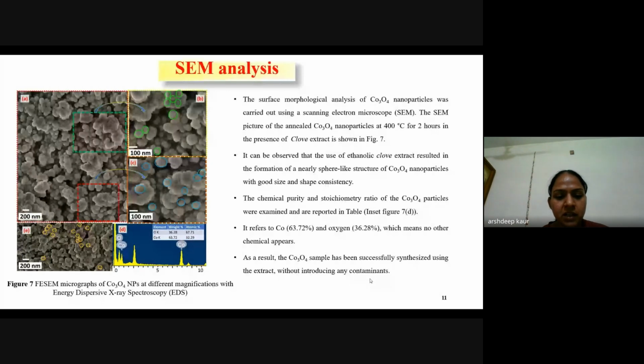In the EDS X-ray spectroscopy, it shows that cobalt has 63.72% and oxygen has 36.28% weightage of the particles, which means no other chemical appears. As a result, the Co3O4 sample has been successfully synthesized using clove extract without introducing any contaminants.